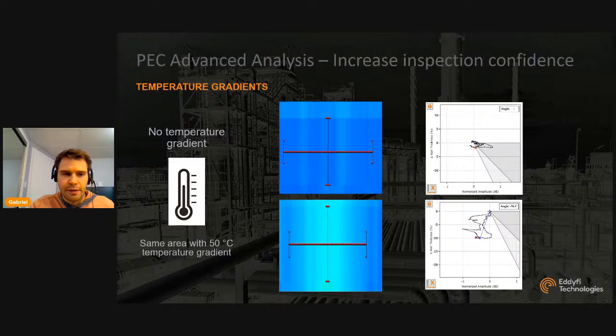Temperature gradients are not very well identified. So here we've got an example. We have a nominal plate, no wall loss. If we apply the PEC tool here, you see the signal is just kind of gibberish. So there's no significant change in amplitude or changes in wall thickness. So we've got just this very localized gibberish in the PEC tool. Nothing to look at, nothing interesting.